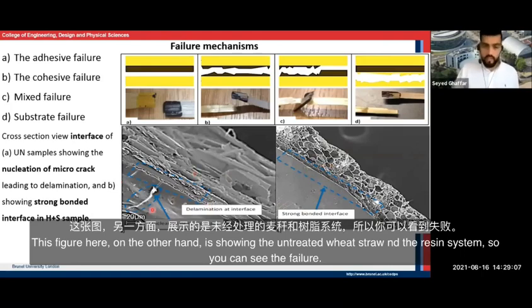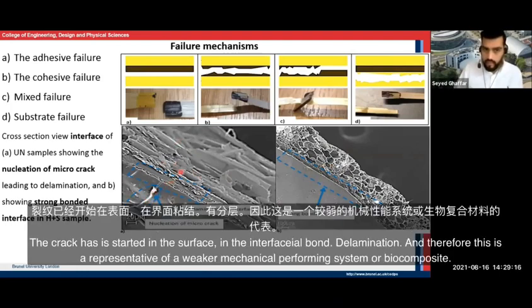This figure here, on the other hand, is showing the untreated wheat straw and the resin system. So you can see the failure, the crack has started on the surface at the interfacial bond, delamination, and therefore this is representative of a weaker mechanical performing system or biocomposite.